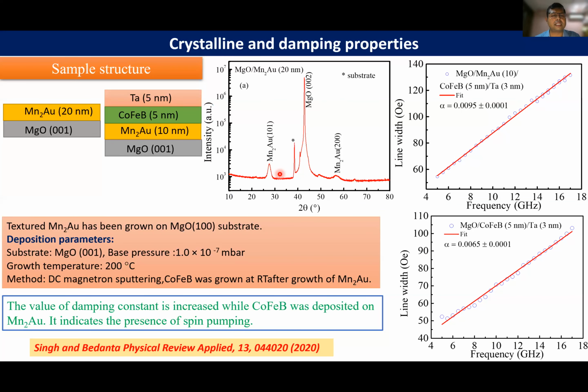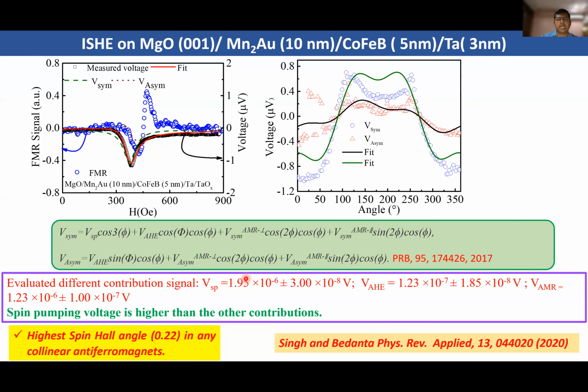For the single layer, you get the damping like this, and when you put the manganese gold, so this is the single layer and this is the bilayer, you get an enhancement of damping that is primarily due to spin pumping, probably. You perform all these detailed angle-dependent ISHE measurements. From that, you could quantify that the spin pumping voltage was higher compared to the spin rectification, and you also observe a very high spin Hall angle.